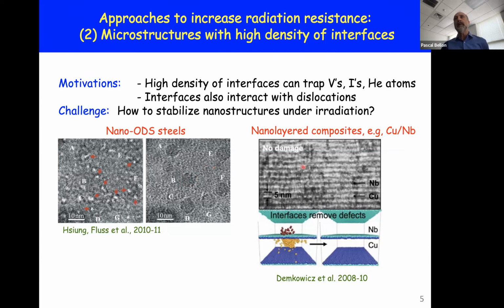Another approach, that in fact was heavily studied at Los Alamos for, say, about 10 or 15 years, is to rely on nano-layered composites. Here's an example of a copper niobium nano-layer.